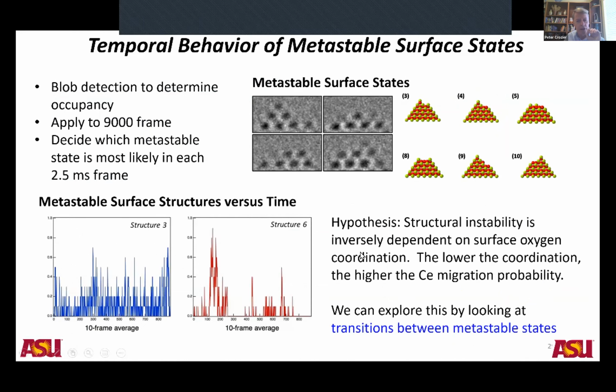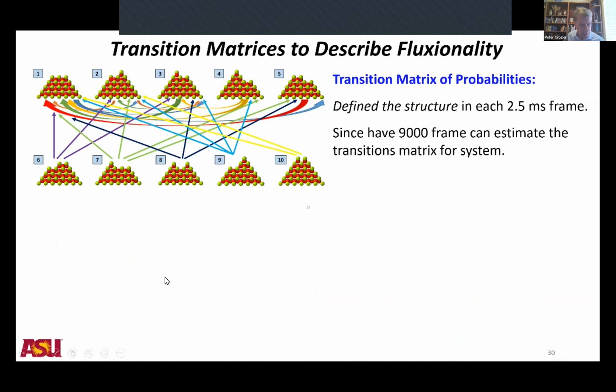And of course, we're trying to understand the interpretation of these metastable states in terms of energetics. And we think that we can interpret the energetics of these states in terms of the coordination of oxygen, whether or not there are oxygen vacancies present or not, because when there are many oxygen vacancies present, that will lower the coordination around this area and increase the probability of migration. So one way that you can explore that is by looking at the transitions between metastable states. And Ramon has done that.